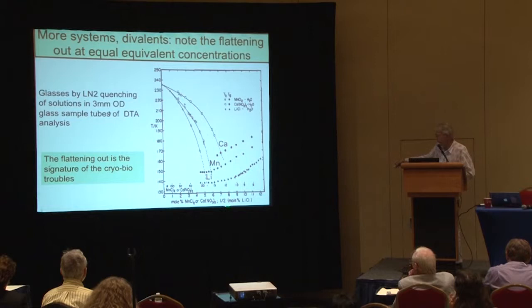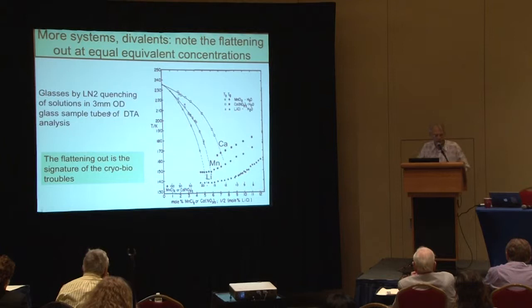And this flattening region here, as you approach there, that's fairly significant. That, we think, is related to the precipitation, in the way that Valeria described, of the pure water as a second phase, droplet phase, being pushed out of solution as we get into this zone approaching the water structure. And I'll show you more details in that later on.